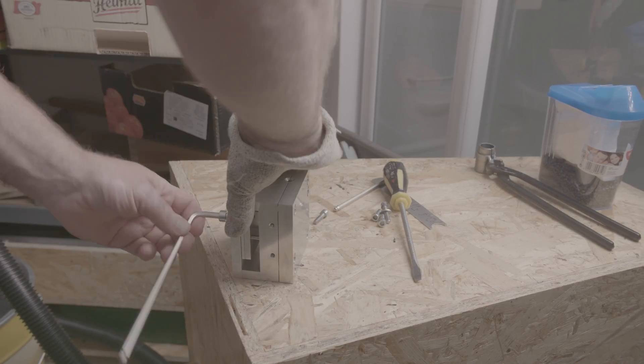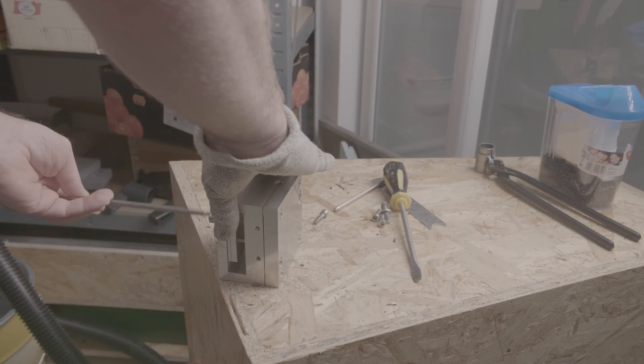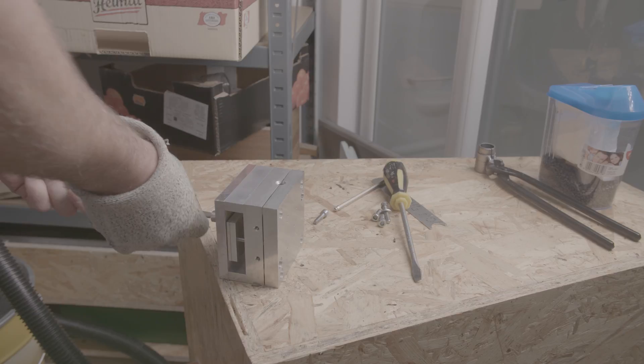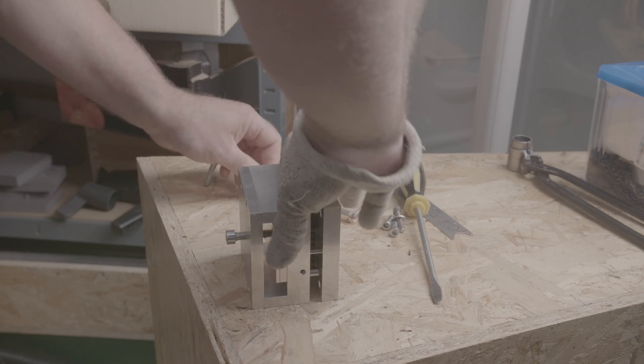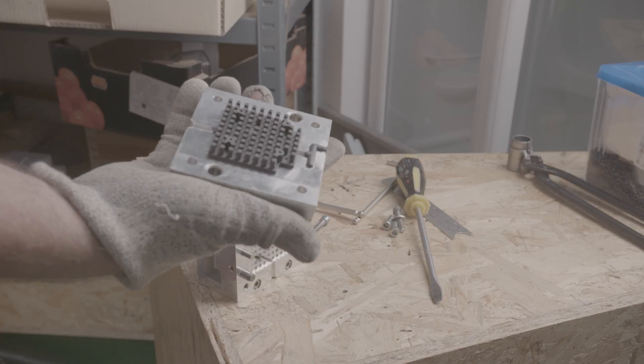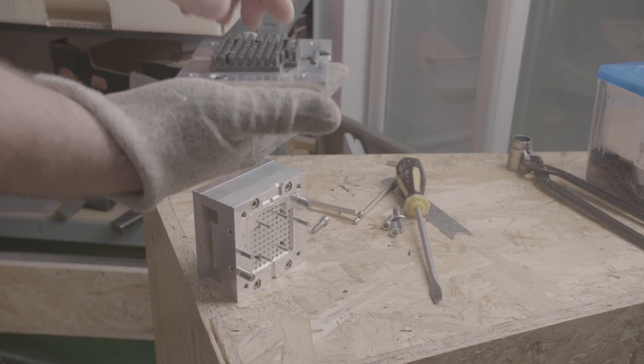And now the next step is, first we're going to try to preheat the cast mold, because currently it was room temperature, which might also aid in not making the form too well-fitting. That's a good idea. And the next stage as well is to instead of 3D printing the mold, we will CNC mill it from metal.